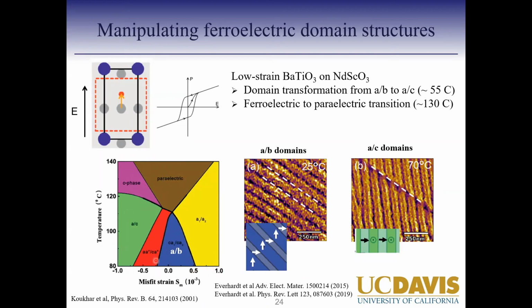And you can control this strain and get different domain structures in this material because the strain in the material can be different, and the depolarization field can be different, and both of these highly affect the domain structure in these materials.